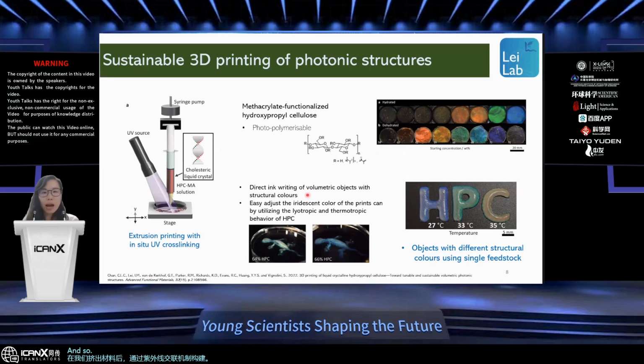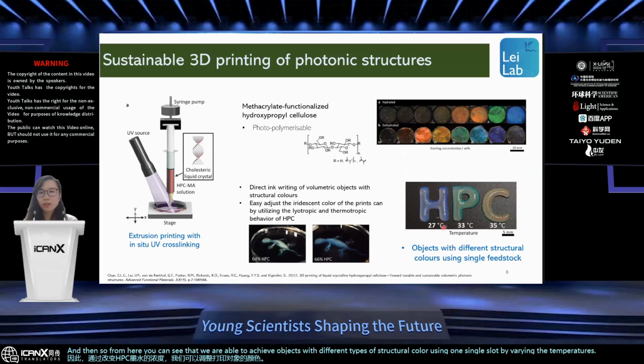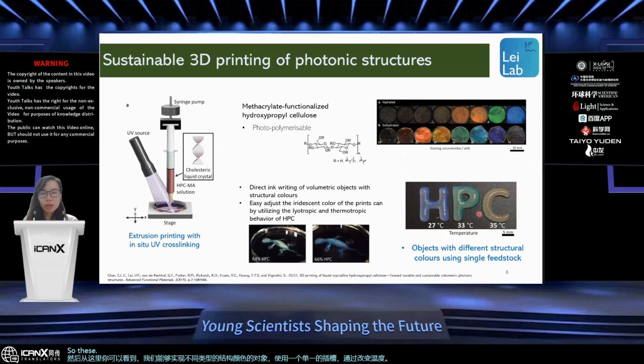And in our work here, we have optimized the cross-linking rate to optimize the color intensity. By changing the concentration of the HPC ink, we can adjust the color of the printed object. From here, you can see that we are able to achieve objects with different types of structural color using one single feedstock by varying the temperature during cross-linking. So these HPC prints are printed with one single material.